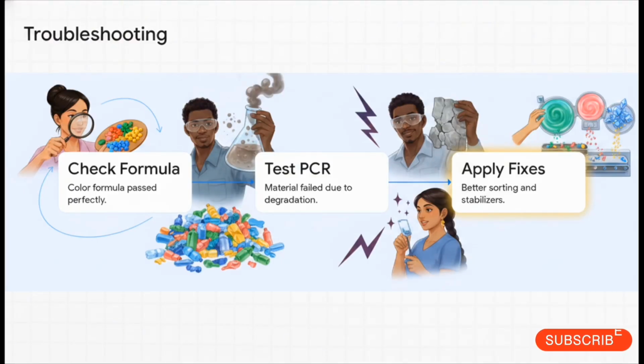Step 1. The team checked the color formula. The result? It passed perfectly. The problem had absolutely nothing to do with the color. Step 2. They tested the post-consumer recycled material itself to check for contamination and degradation. The result? It failed miserably. The PCR material was highly degraded.